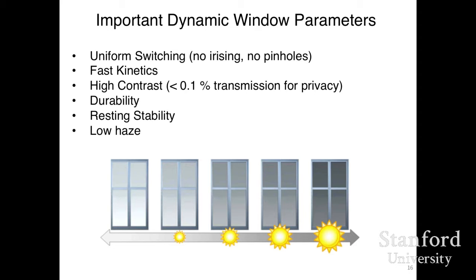And then I've highlighted that very high contrast is needed, particularly if privacy is needed, say in a residential situation. You have to go below 0.1% transmission to create a state where people outside can't see in. And then, of course, the windows need to be durable. They should be stable in the resting state, meaning that if you turn it dark, it will stay dark, preferably without having to continue to apply power. And then it's very important that the windows have very low haze, in other words, that they not scatter light.